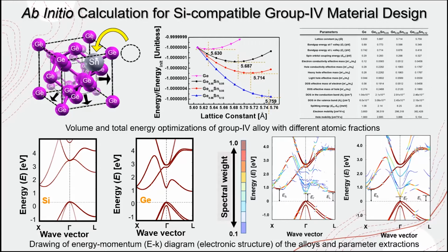Group 4 includes carbon, silicon, germanium, and tin on the same column, and they are believed to be silicon compatible because they have 4 outermost electrons. So if you perform the ab initio calculation of a certain material, you can minimize the volume. In other words, you can minimize the system energy, total energy, and determine the atomic distance between adjacent atoms. And based on the structural optimization, we can extract well-known material properties like electron affinity, electron and hole mobility, energy band gap, things like that.